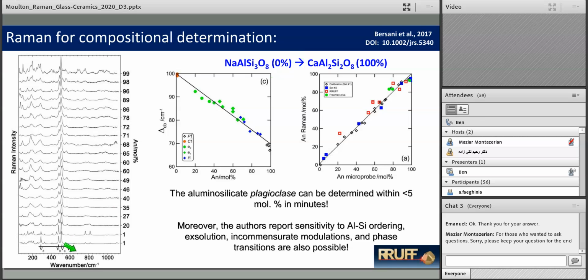In the plot here, we see our Raman spectra with the various peaks. We have 0% or 1% anorthite here, all the way to basically 100% anorthite at the top. And Bersani et al. have created a standard based on this parameter delta CB. This delta is a function of the peak positions here, which I haven't put on the plot. But the peak positions ultimately shift linearly as a function of composition.